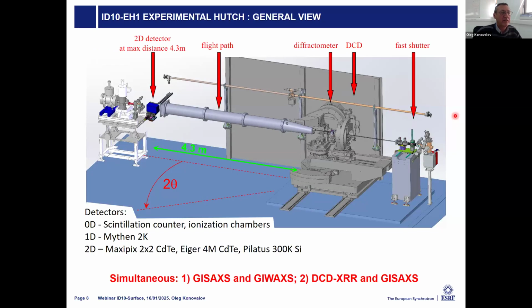And here you can see a bit more in detail what we have in the experimental hatch. So at the beginning of the hatch, we have a fast shutter. The fast shutter is needed to stop the beam when we don't measure. Like this, we protect the sample, and also we protect the detectors. Then another element which I already mentioned is the double crystal deflector. We work on liquid surfaces the majority of the time at this beamline, so we need to tilt the beam. It's not trivial to tilt the synchrotron and not trivial to tilt the liquid surface. So we need to tilt the beam. And for this, we have this special device, which we call the double crystal deflector. And how it works, I will tell you a bit later.